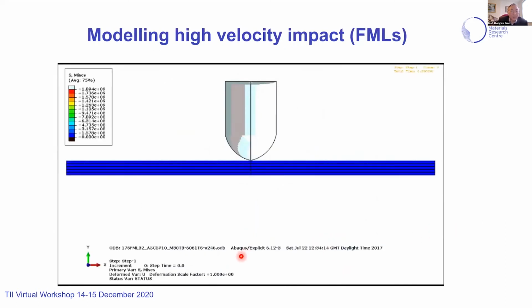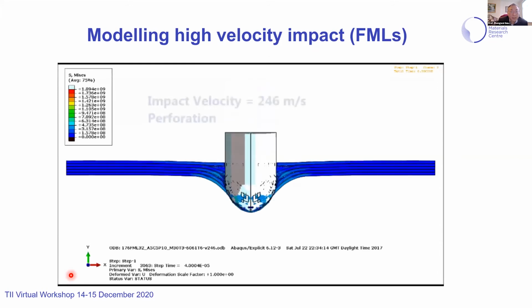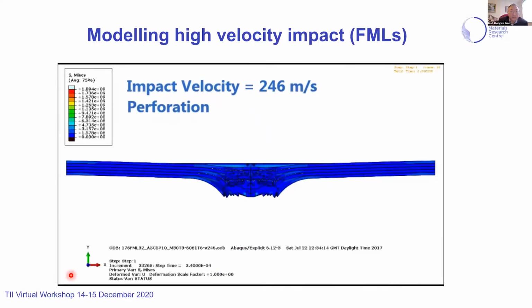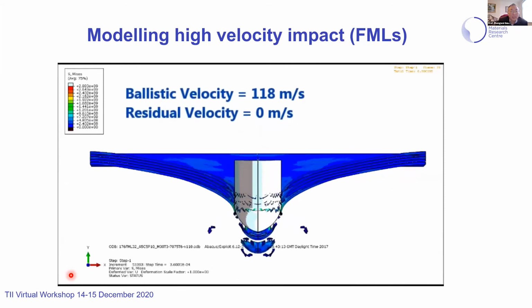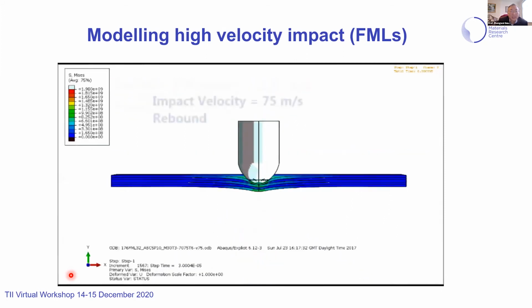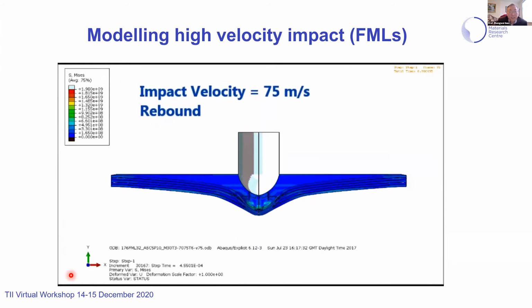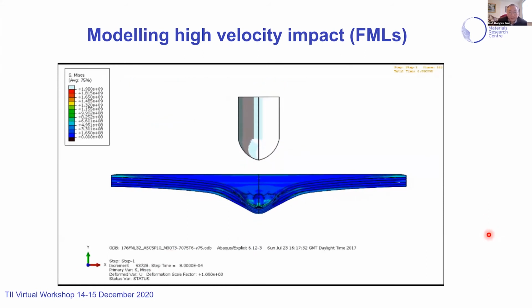This modeling shows different impact velocities. With high impact velocity, we get full perforation; at the lower one we get just perforated; and at the lower velocity the projectile actually bounces back. So this 246 is fully perforated, around 118 meters per second is just perforated, and 75 is not perforated, so it bounces back.